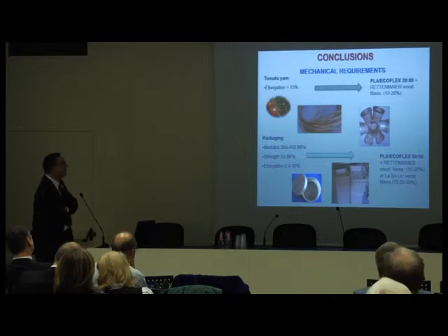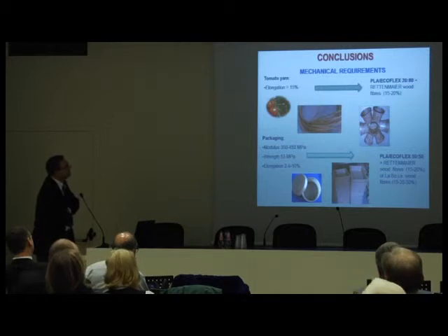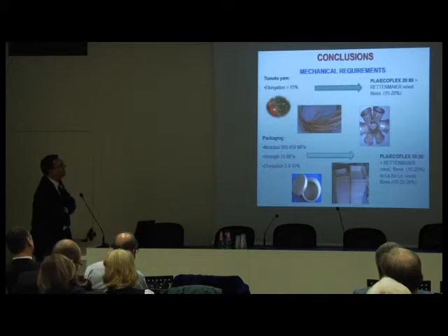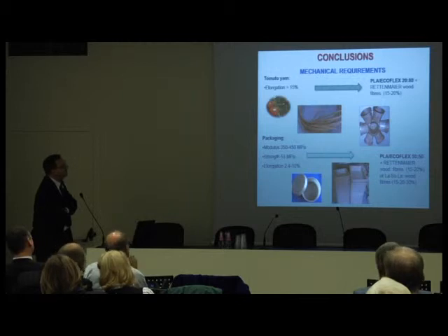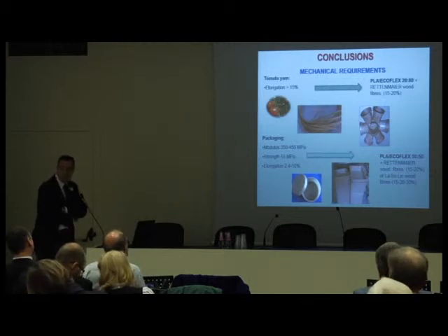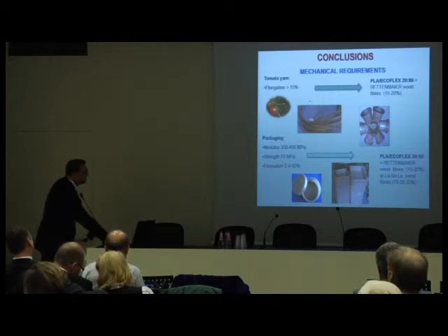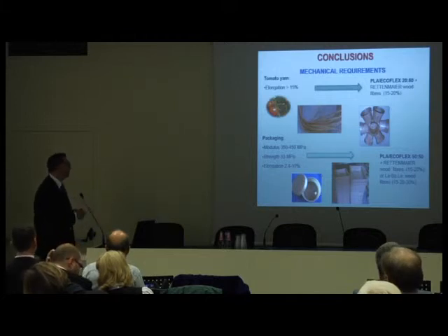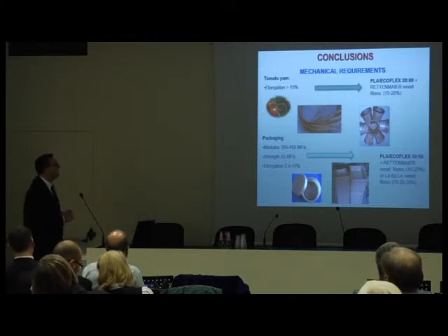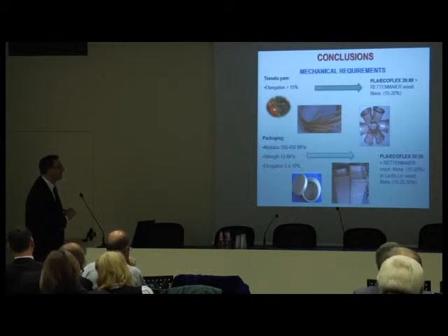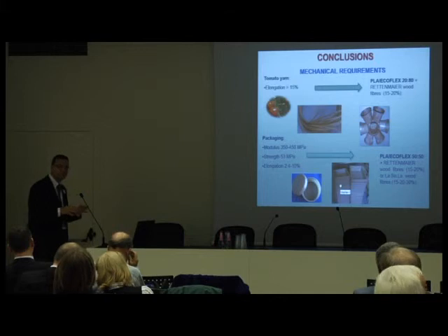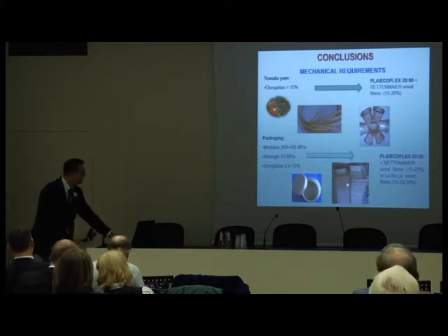Also, for pots we use the same composition, 20-80 PLA Ecoflex, because for injection molding applications, when we add 20% fibers, the other formulations were too brittle. This instead was quite good. Also, for other types of packaging, we have a cosmetic box. This is made of PLA Ecoflex 50-50 with Rettenmaier fibers, and also trays for food. This is made with the same formulation.